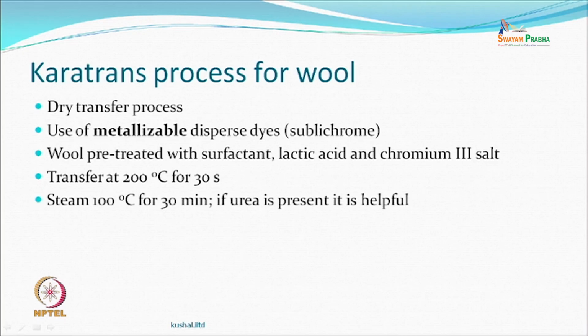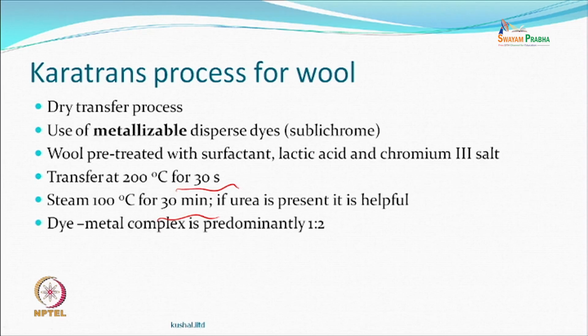So there is a post-treatment which is a long period. So you can appreciate it cannot be a process which is as fast as the dry transfer. After the transfer has taken place, you are still going to steam. Look at the comparison: 30 seconds versus 30 minutes for fixation. Urea may also be available in the pre-treated material, and then wash it off.